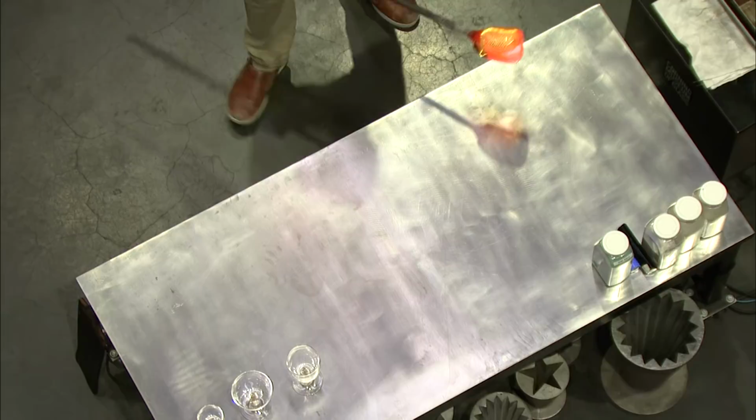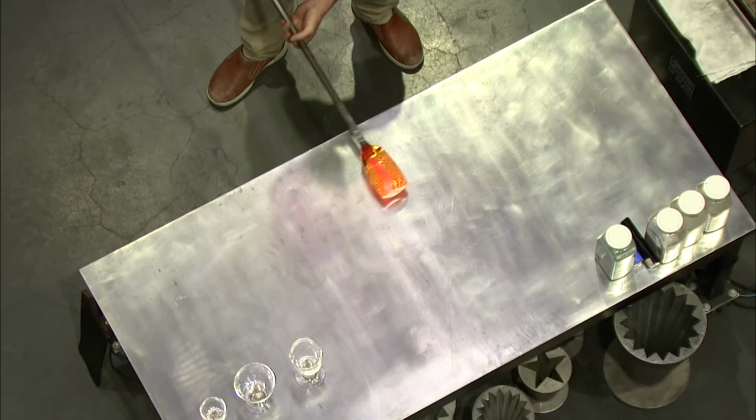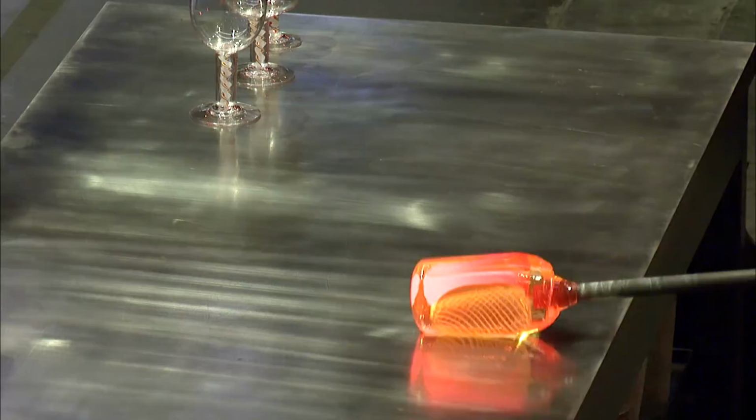So this will be enough for this cane pull. We have two cane ladders set out on the floor here in the amphitheater. So I don't think it'll be a super long cane pull. We want nice dense saturation in the color for the rainbow of this piece. We want to really be able to see that rainbow. It is possible to pull and stretch that color a little bit too far and have it kind of fade away. So in this case, we'll keep that color really nice and dense. We won't stretch it too far, but we're just looking for this beautiful spiraling rainbow.